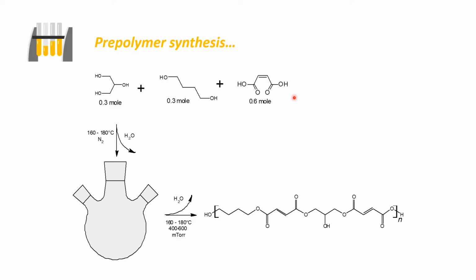So, how do we synthesize the prepolymer? Prepolymer synthesis is done by mixing 0.6 mol malic acid with 0.3 mol glycerol and butanediol in a 500 ml flask, processed at 160 to 180 degrees Celsius for considerable time under a nitrogen atmosphere. Lower temperature is more convenient to hinder the possibility of cross-linking.